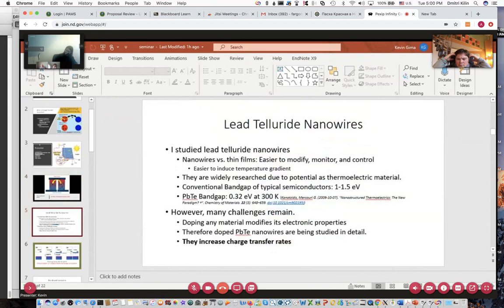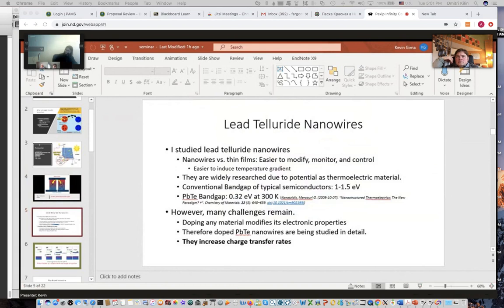Okay, so lead telluride nanowires. For what project am I studying the lead telluride nanowires? You might ask, why am I studying the lead telluride nanowires as opposed to thin films? Essentially because the nanowires' electronic properties are easier to modify, monitor, and control. Especially in nanowires, it's easier to use temperature gradients, so it's easier to study the thermoelectric effect in nanowires than it is in thin films. They are widely researched by scientists and researchers due to their potential as a thermoelectric material.